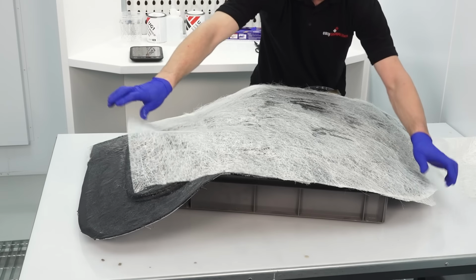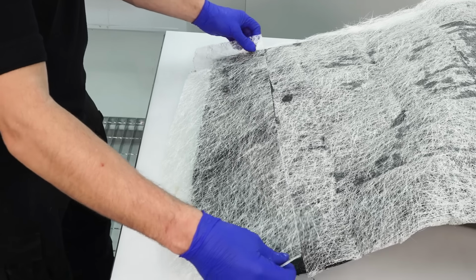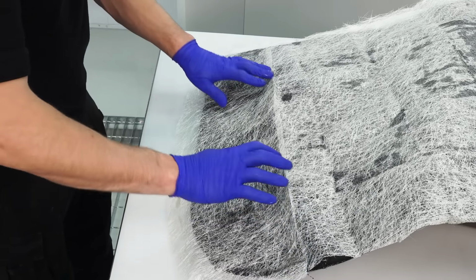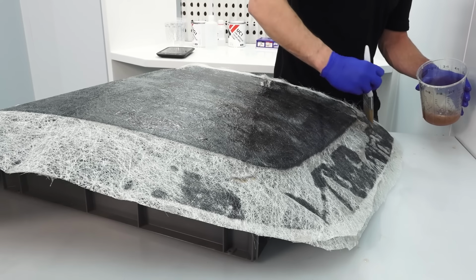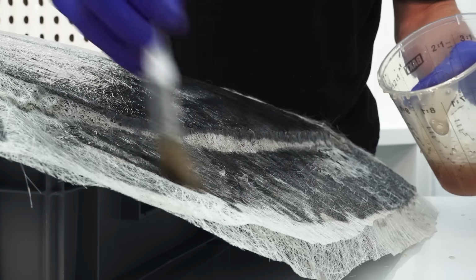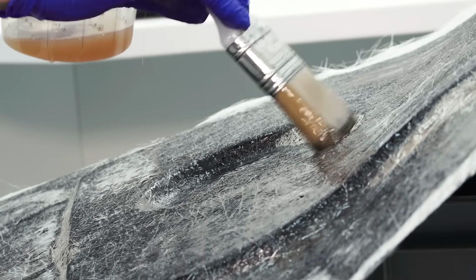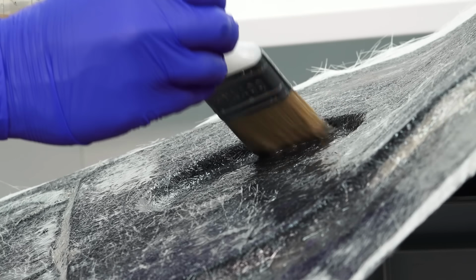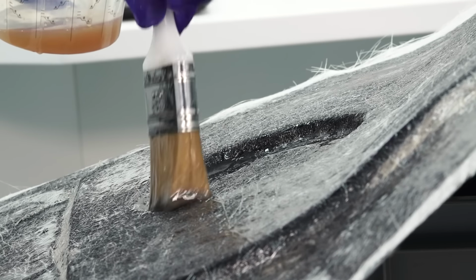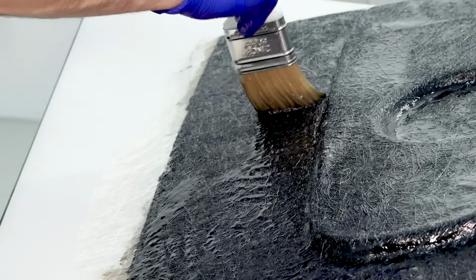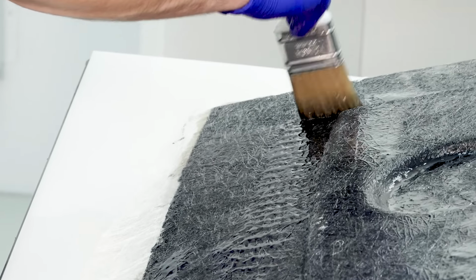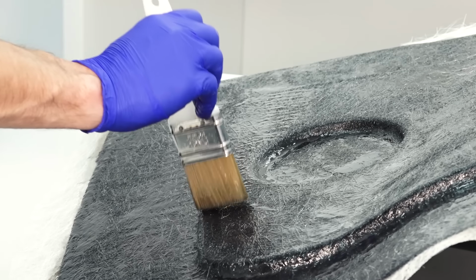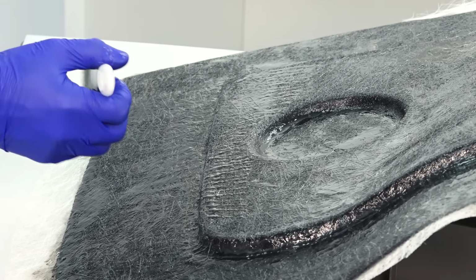More resin is then applied and the second ply is wetted out and laminated in just the same way. This lightweight 100 GSM matting is used for these first layers as it does conform really well to intricate details and it creates minimal print through onto the surface of the mould. Unlike the tooling resin, which we'll be using later, the coupling coat has very good transparency, meaning that any dry areas or bubbles can easily be identified and worked out.